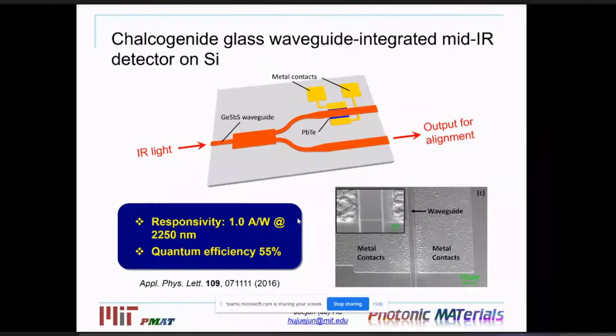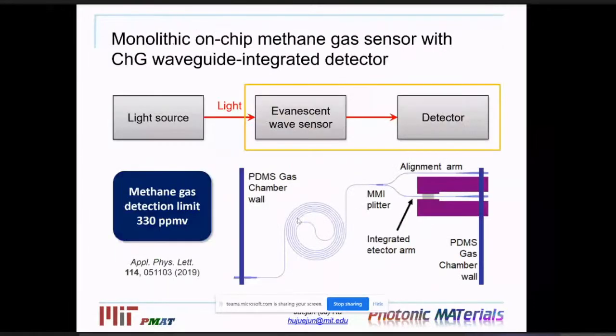Our natural next step is to integrate such a detector along with the evanescent waveguide sensor to create an on-chip detector-integrated sensor for methane gas. In this experiment, we put together these spiral-shaped waveguides along with on-chip detectors, and we then encapsulate everything with a gas chamber to allow continuous flow of different gas species. Using this device, we were able to demonstrate real-time detection of methane gas down to a detection limit of about 300 parts per million. And this can be further improved if we improve the stability of optical coupling between the light source and the on-chip waveguide, to avoid intensity fluctuation due to this off-chip coupling process.